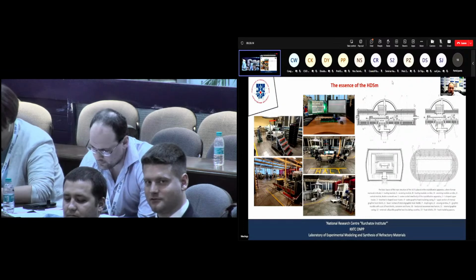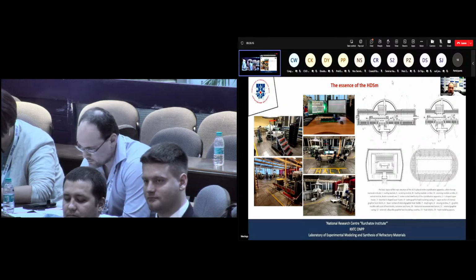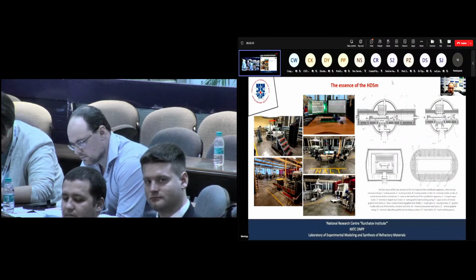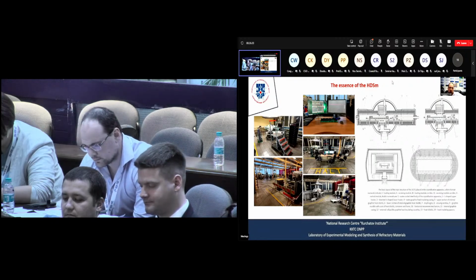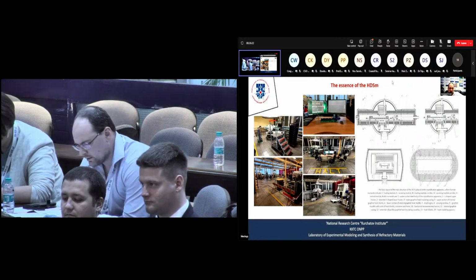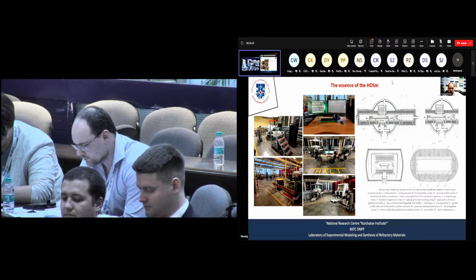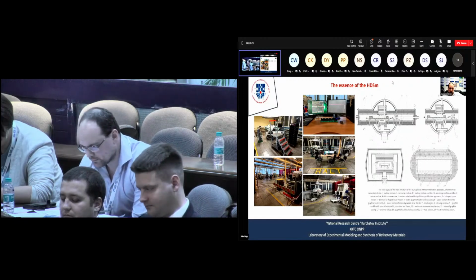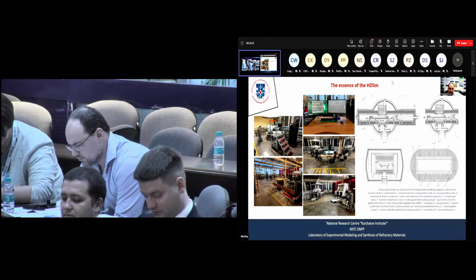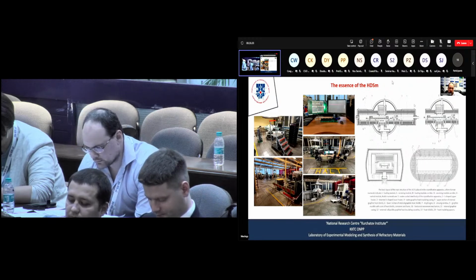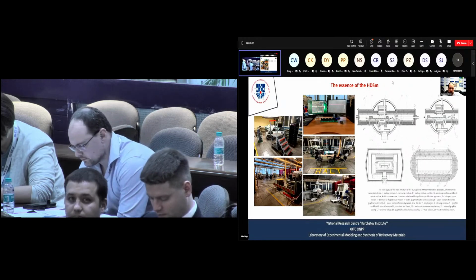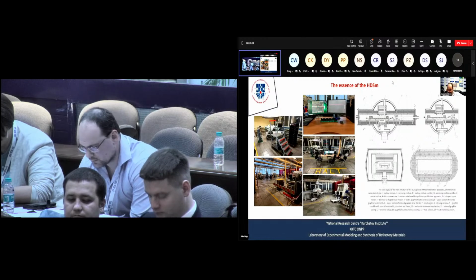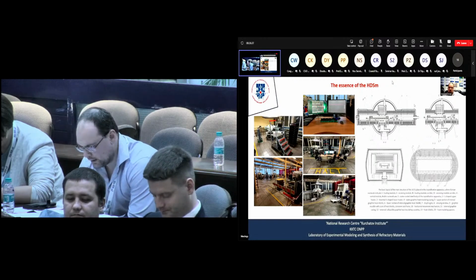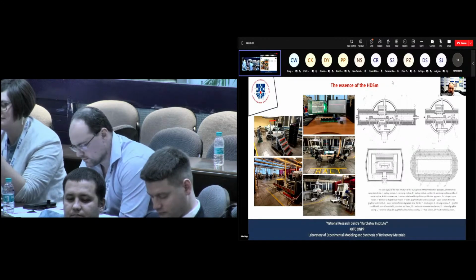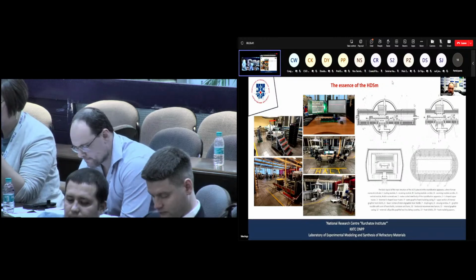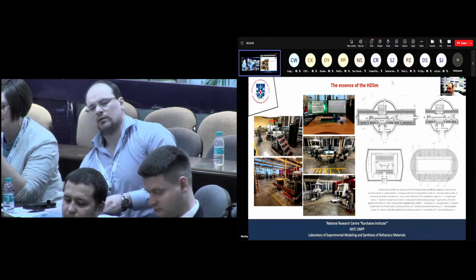The main difficulty of this method is the creation of the thermal unit. The thermal unit should provide a high temperature gradient region in the crystal growth zone and necessarily a low temperature gradient region in the crystal cooling zone. This condition is very important for obtaining optically perfect fluoride single crystals. To fulfill this condition, a carbon graphite thermal unit was proposed and developed in several modifications, as depicted in the slide.